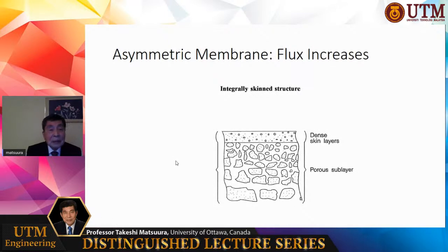Now, if the membrane thickness is very large, then the productivity of the water by the membrane becomes very small. So you have to make this layer of very tiny pore as thin as possible. But if it is too thin, it will be too weak. You cannot apply pressure. So it is supported by a porous sublayer, which has many much larger pores. So this dense skin layer has small pores, and this porous sublayer has very large pores. And mechanically, the membrane is strong enough. Well, this structure is called asymmetric membrane structure. And by this way, flux could increase.